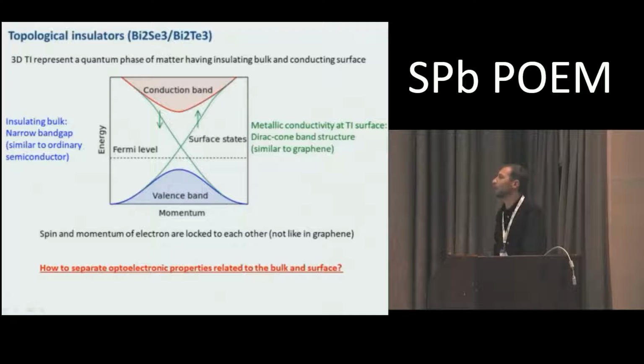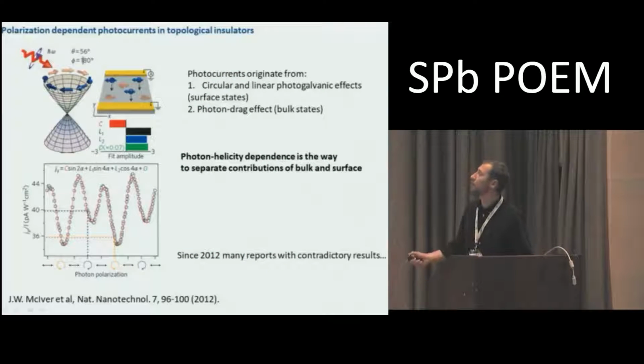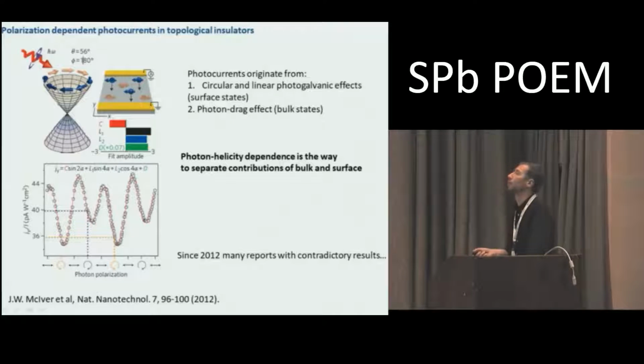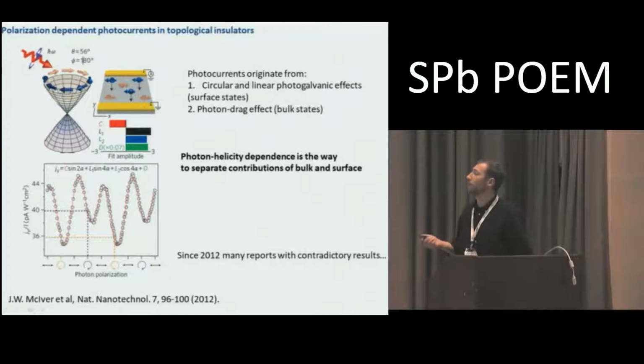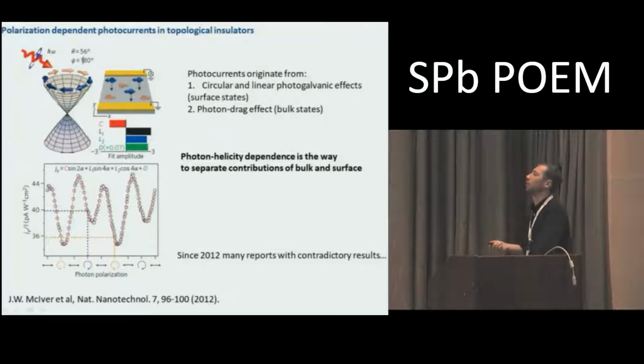And there is a reasonable question: how to separate optoelectronic properties related to the bulk and surface. In 2012, it was suggested that by measuring the helicity-dependent photocurrent, it is possible to separate these contributions. Indeed, if we observe some photocurrent which is dependent on helicity of light, we can say that this current is related to the spin-split surface states. And the photocurrent which does not feel the helicity of light should be related to the bulk structure. Since that time, many contradictory reports were published. Some people were observing this helicity dependence, some not.